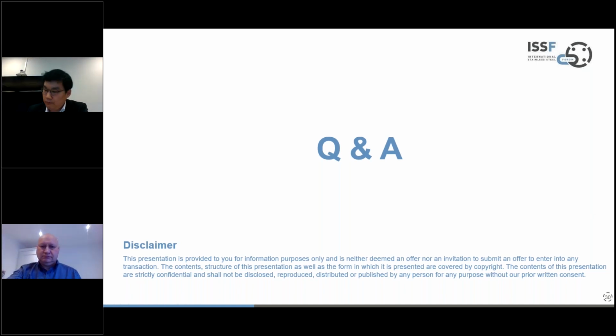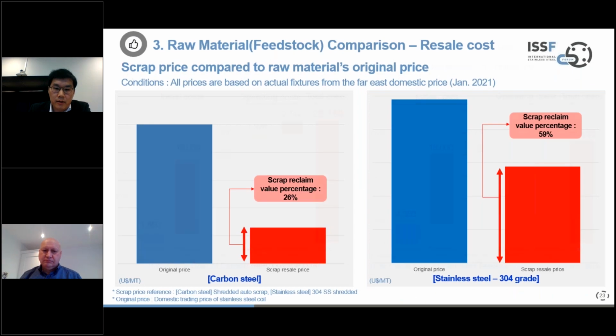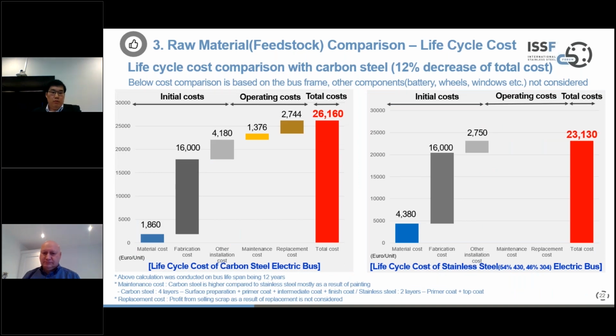Why is the other installation cost of stainless steel cheaper than that of carbon steel? Yes, I will go back to that page. With regards to other installation costs, if we look below, it's mostly because of the result of painting. In the model that we used for carbon steel, the amount of painting required as compared to stainless steel has to be more. There are 4 layers in this procedure for carbon steel: surface preparation, primer, intermediate, coating. In comparison to that, stainless steel had 2 layers, primer and top coat. This was the major reason why there was a cost difference for the same procedure.